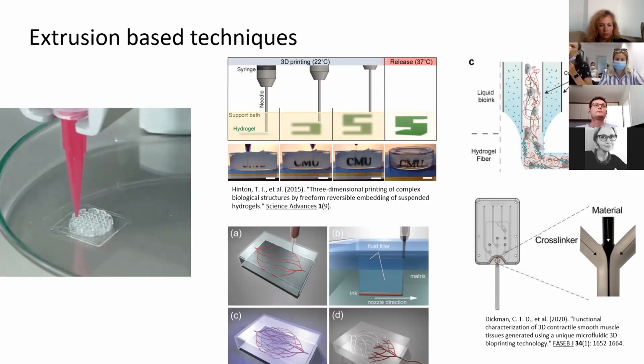The most easily understandable is extrusion-based bioprinting, which is very similar to FDM 3D printing, as you would know from fab labs or maker spaces. So you have material in a cartridge and then you extrude it through a nozzle, and if the nozzle is moving over a surface, then you deposit material. And this is a very interesting technique. It's probably the most widely used of them all. It's relatively cheap. It is compatible with a really broad range of materials. So you can use hydrogels, silicones, other types of materials.